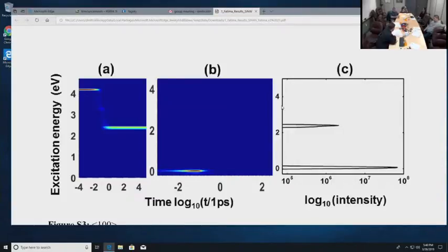But later, there were enthusiasts who have written a little script that executes VASP and uses it for finding transition states. And they use an algorithm that connects reactant and product by a sequence of geometries, and then computes the energy of each point on this trajectory and then tries to nudge these points of the trajectory a little away and optimize it in such a way that the barrier height along this trajectory will be minimal. And then they report the height of this barrier as the activation energy.